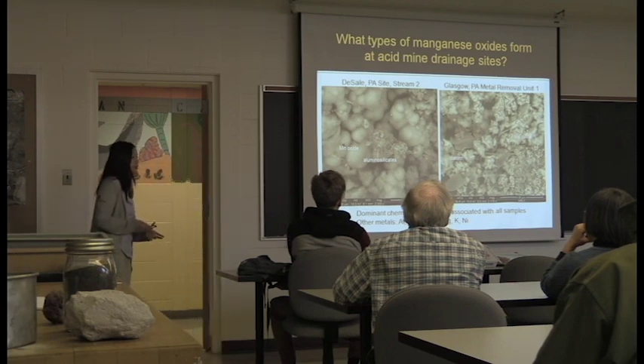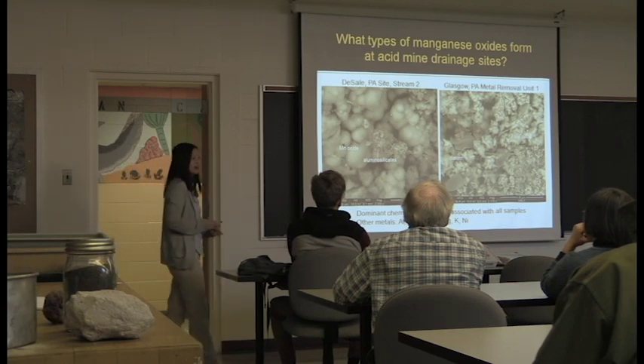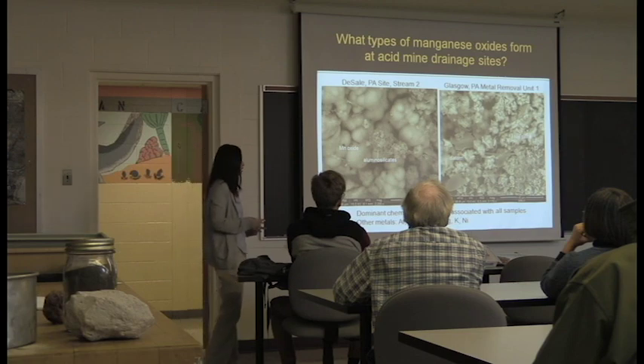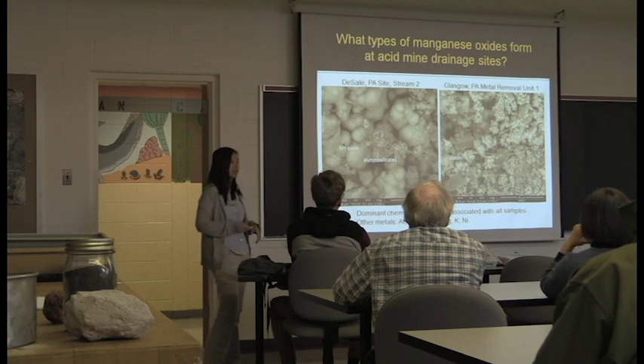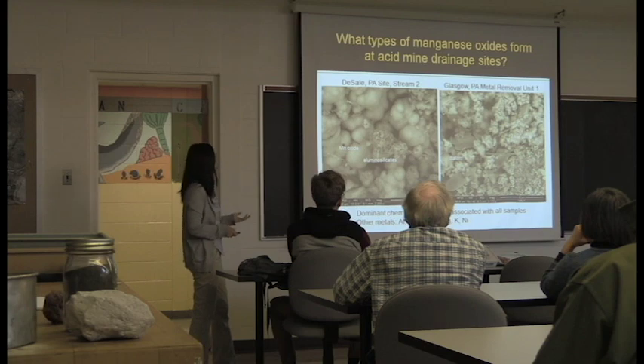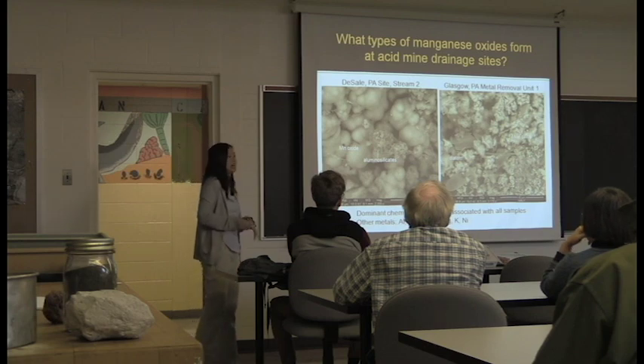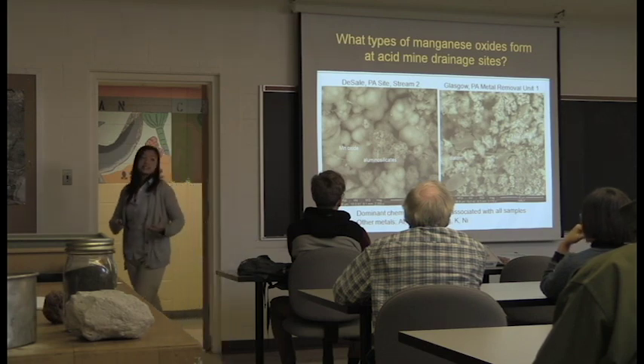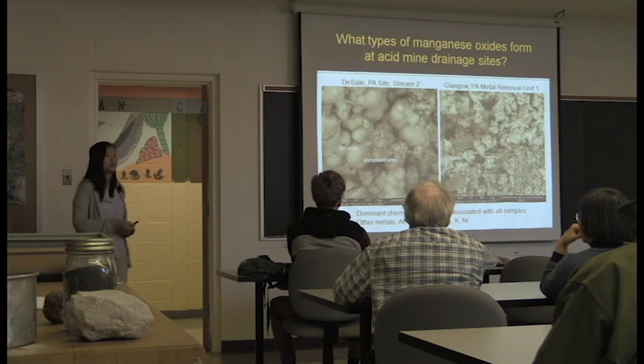As far as chemistry goes, all of these have manganese, they all have oxygen, which is not surprising, these are manganese oxides. They also have calcium, which is because there's a lot of dissolved calcium in the system as a result of the limestone everywhere. But the great thing is we also find a lot of metals associated with these manganese oxides, including aluminum, iron, zinc, lead, magnesium, potassium, nickel, etc. So that's telling us that these manganese oxides are doing their job.